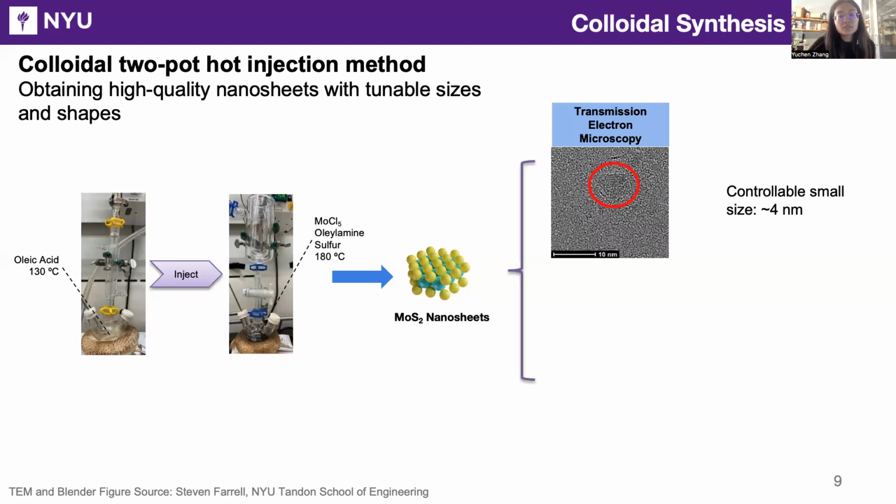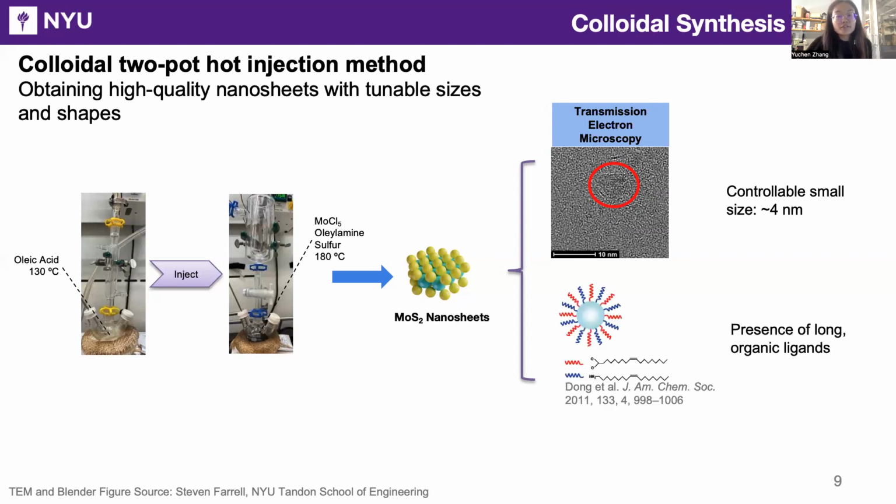Using this colloidal synthesis, we can achieve a controllable small size of the nanoparticles, about 4 nanometers. This is ideal in terms of catalytic performance and surface free energy. However, a problem related to this colloidal synthesis is the presence of long organic ligands attached to the particle surface.